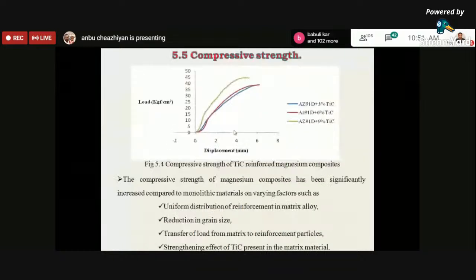The compressive strength of titanium carbide reinforced magnesium composites has increased comparatively with monolithic materials. This is due to uniform distribution of reinforcement in the matrix alloy, reduction in grain size, transfer of load from the matrix to the reinforcement materials, and the strengthening mechanisms. This acts as a barrier to the dislocation movement, and hence the grain size has been reduced. Due to that, the compressive strength of the synthesized composites has increased.